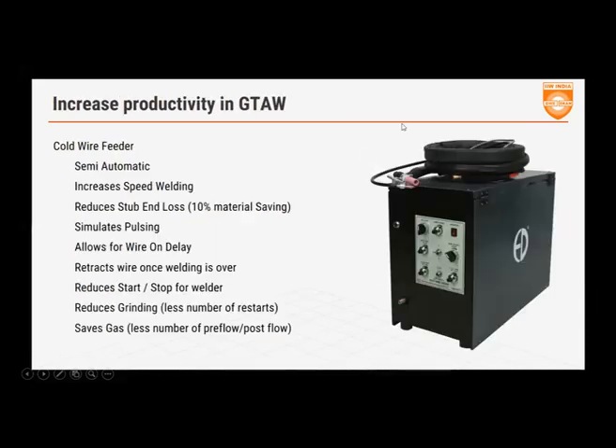Now, the last two points we have: because the welder now has fewer starts and stops, once he starts welding, he can continue till the time he feels comfortable. The wire is not finishing. He doesn't have to stop every 2 minutes to pick up the second wire. The wire is coming continuously. It allows him to weld faster. This reduces his fatigue and allows him to weld continuously. Each start-stop that you don't do, you save gas because you don't have so many pre-flows and post-flows happening. That saves time, and it also saves you time on grinding at a later stage because you will have fewer high points and fewer start-stops.